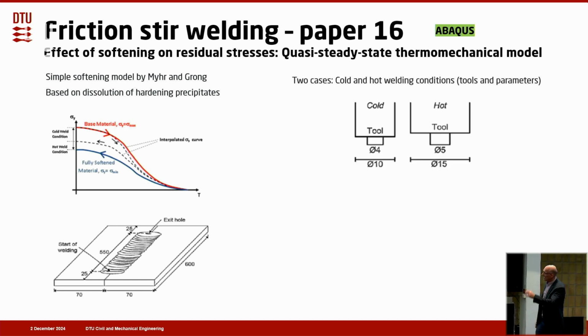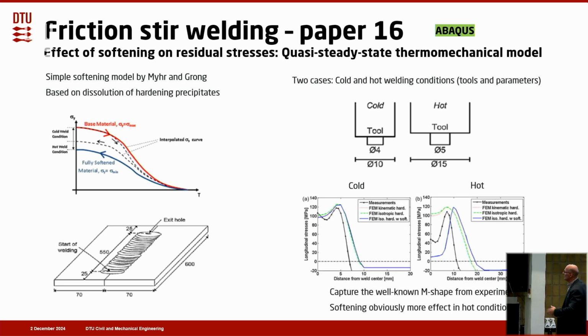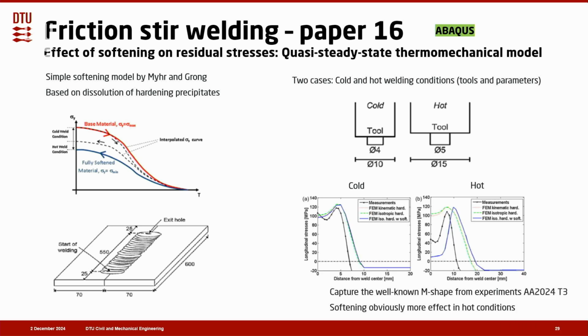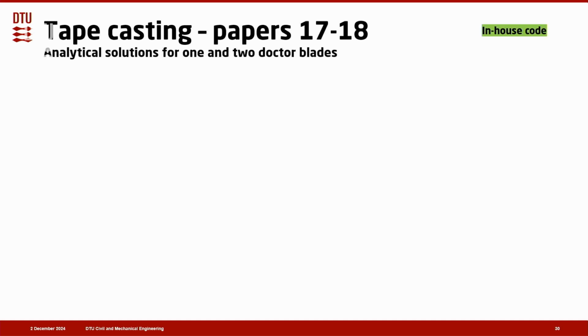And we had two cases, cold and hot welding conditions. And we were actually able to capture the well-known M shape from experiments that you actually see in literature. And of course, the softening was obviously taking more effect during the hot conditions. That is, of course, expected. So then I come to the next process, tape casting.